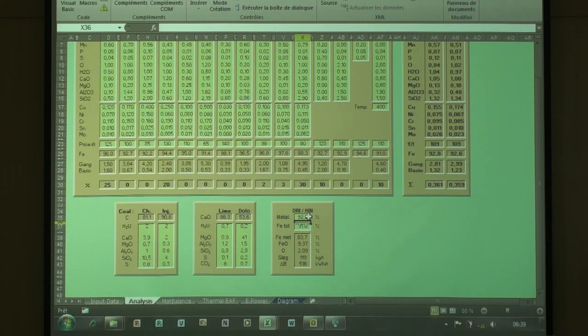You mean from total FE? Utilization rate. Oh, you have 90%, let's say. So you have 12% FEO in the raw material. If you take this 12% FEO and you put this directly into the slag, you will have 50% FEO in your slag, or 60% FEO in your slag. And you increase the slag amount, so you will lose a lot of material.